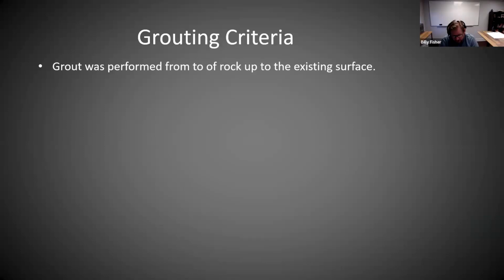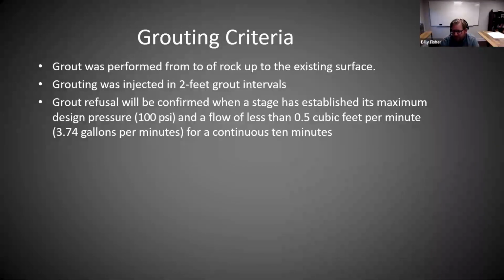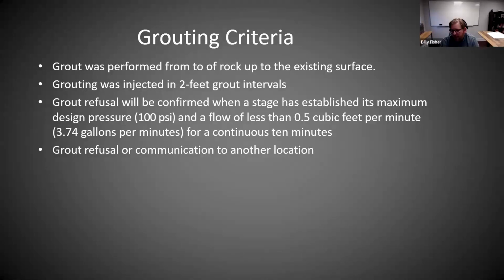So the grouting criteria - how did we determine that we had grouted everything properly? We were going to grout from the rock to the surface, in 2-foot intervals. We would grout, and once we hit our cutoff criteria, we'd come up 2 feet, and so on. We determined we would do it based on shooting for 100 psi, with a flow of about 0.5 cubic feet per minute for 10 minutes. Then, if we had refusal, ground refusal, or communication with another location, that was another criteria to stop grouting, or if we hit an ultimate pressure of 200 psi.